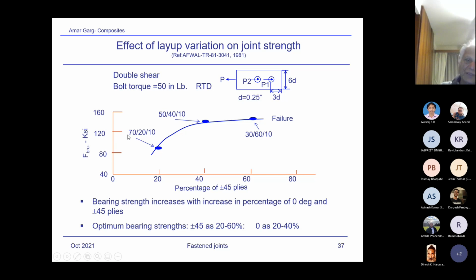So in this case, suppose it had 10 plies, that means 7 plies will be 0, 2 plies will be 45s, and 1 ply 90. Here you will have 5 plies zeros, 4 plies of 45s and 1 ply of 90. So what we are trying to say, if you have too many zeros, on one hand, of course, 0 degree is good for the load carrying capability. However, the bearing performance deteriorates because that leads to the shear out failure.